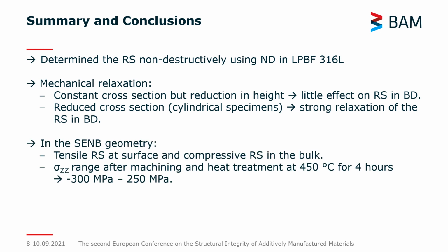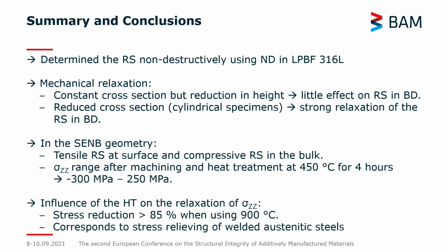In the SENB geometry, we've observed that we have tensile residual stresses closer to the surface that are balanced with compressive residual stresses in the bulk. This is the way the residual stresses distribute in laser powder bed fused specimens. And we've seen that although these SENB geometries were heavily machined and had been heat treated at 450 degrees for 4 hours, there are still compressive stresses of up to minus 300 megapascal that are balanced with tensile residual stresses of 250 megapascal. By applying additional heat treatments, we've seen that a stress reduction of about 85% can be obtained when using 900 degrees, which corresponds well to stress relieving suggestions for welded austenitic steels.